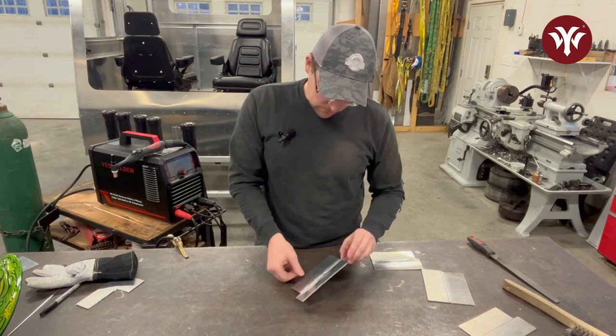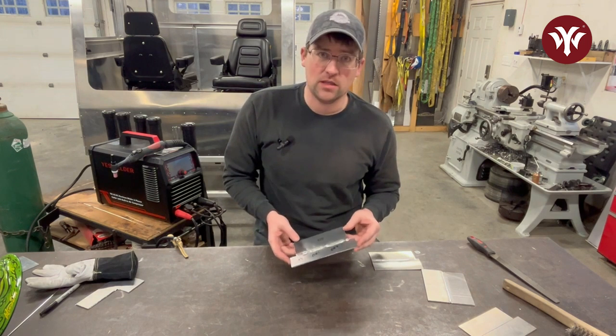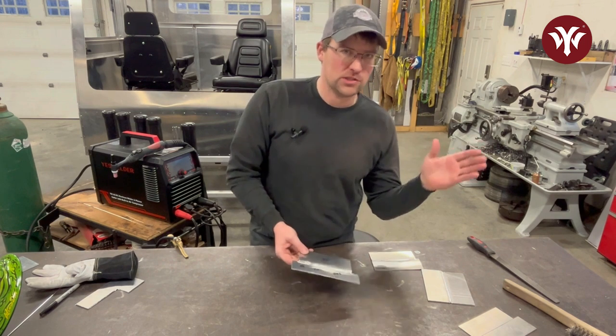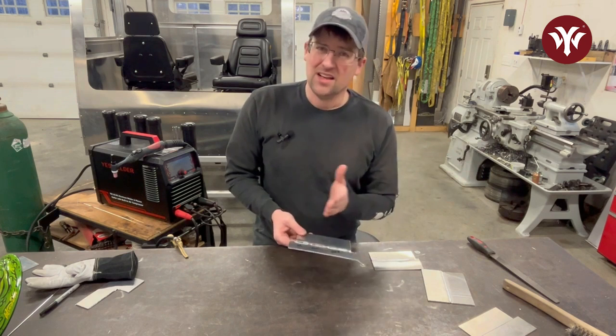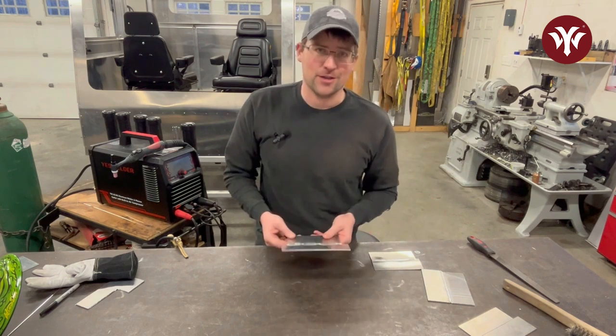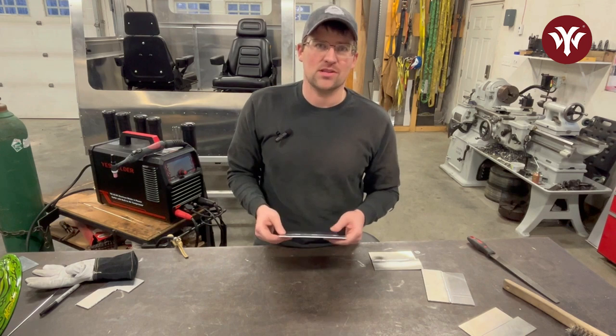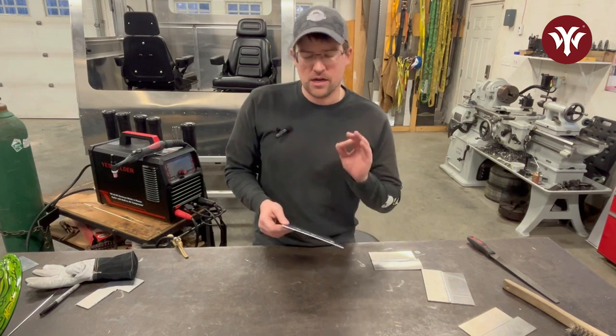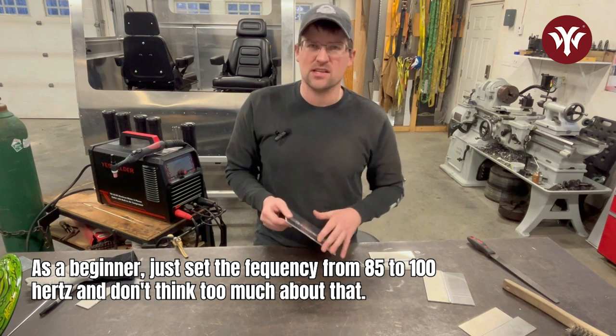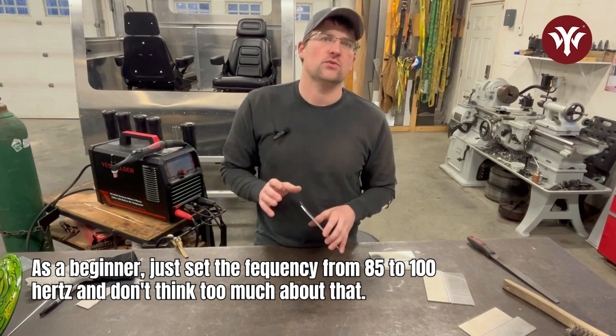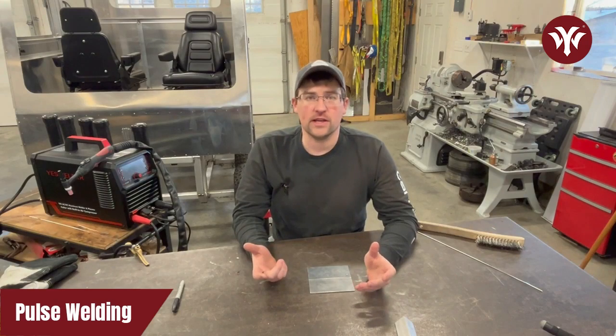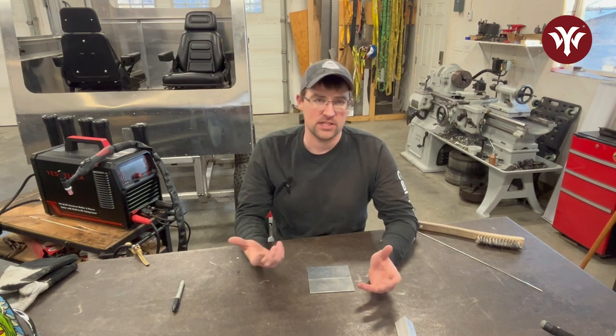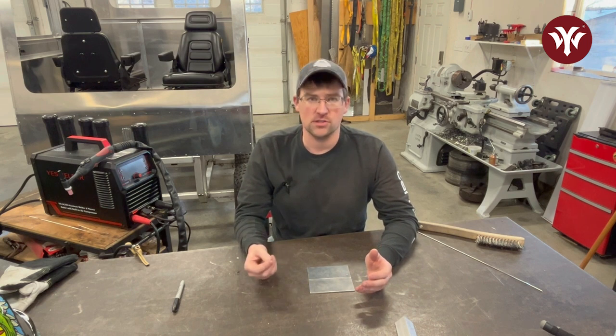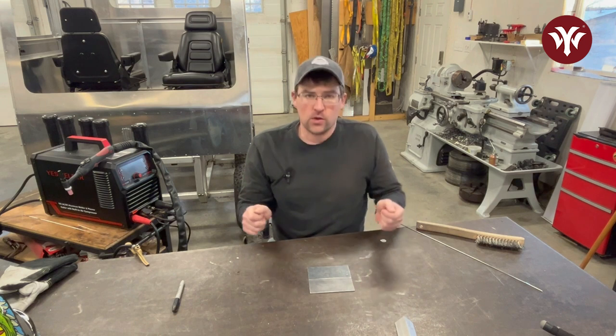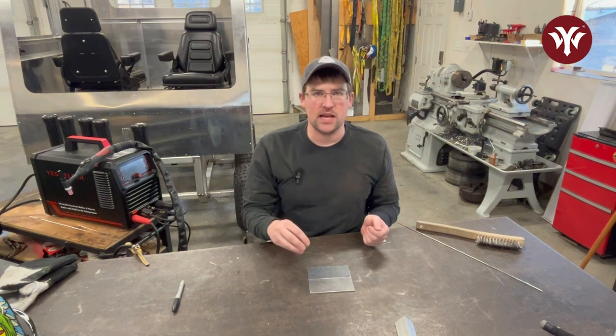And so if you're trying to weld some really thin material, you're probably gonna be going to a higher frequency. But there's the reason they say 85 to 100 Hertz is really where you wanna be most of the time. And as a beginner, just set it there and don't think too much about that. Frequency is not a setting you're gonna need to adjust very much. Then another thing we'll get into after this is playing with the pulse settings, because this is a AC/DC TIG, but also AC/DC pulse TIG, which means when you're welding that puddle, it's not gonna be just a steady arc.